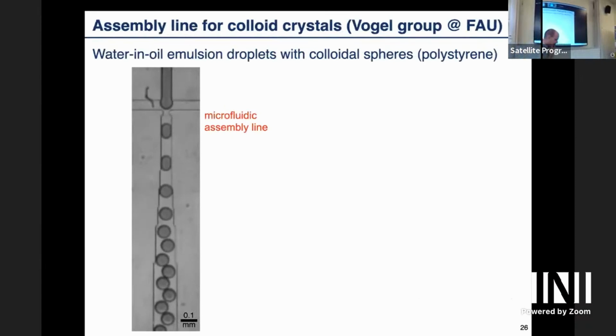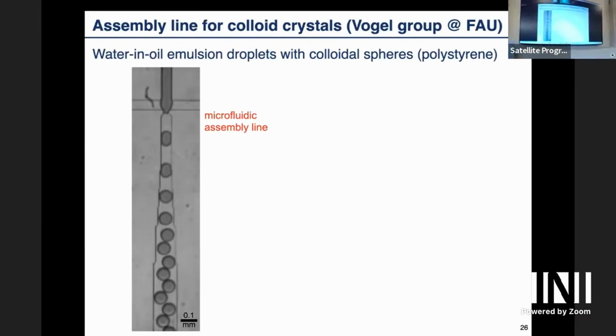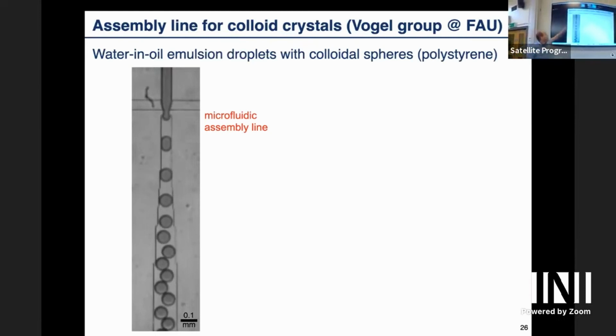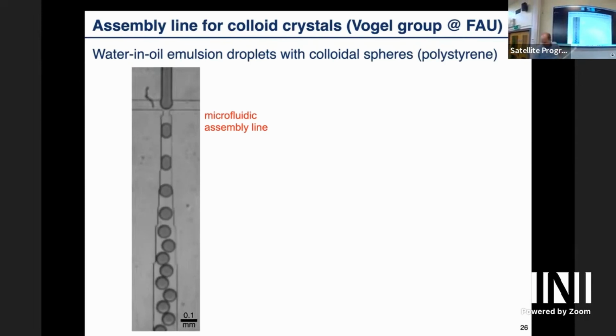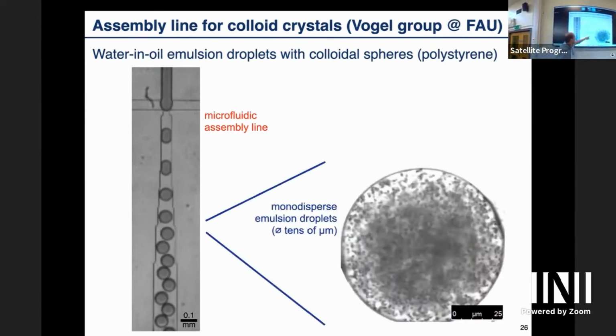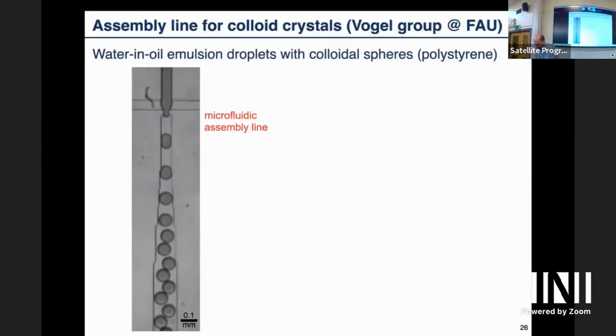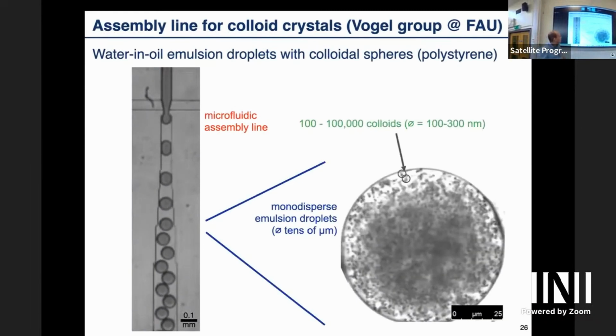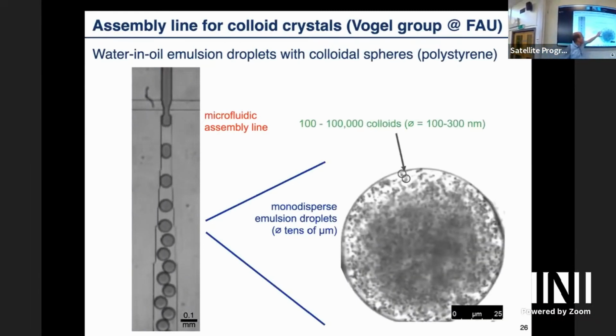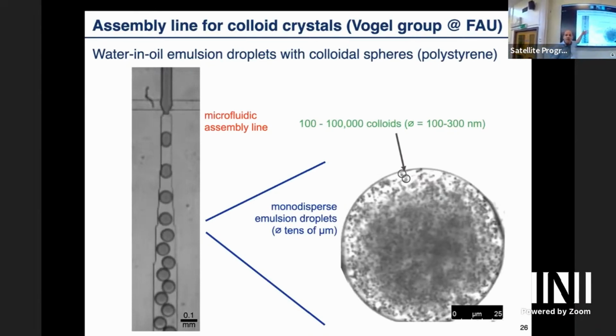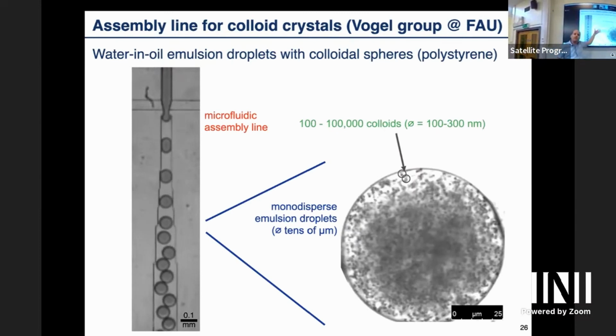So my colleague has this assembly line for colloidal crystals. This is microfluidics. So this is water in oil, and in these water droplets, it looks like this. So you have a monodisperse emulsion of small colloids. There are polystyrene colloids, roughly 100 to 100,000. We can control the number by controlling the size of the droplets and the concentration of the colloids in solution. Of course, it's not accurate, but you get some distribution and you can control it somewhat.